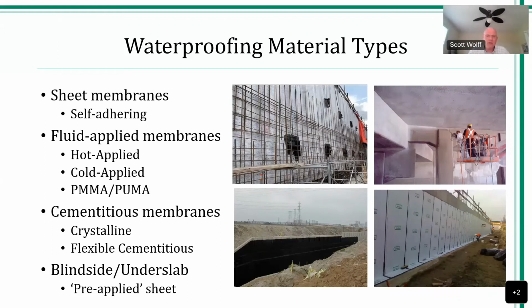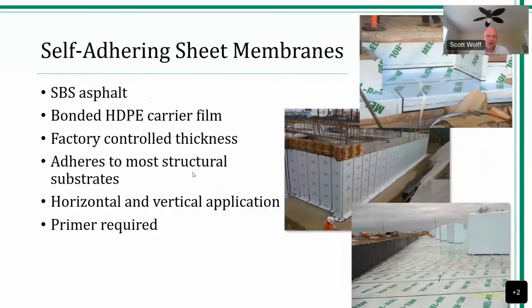And then the blind side under slab systems, the pre-applied sheet, are used again in high hydrostatic water conditions. We had a project on Biscayne Bay that had it 60 feet below grade right there on the bay. So obviously we completely bathtubbed that entire structure. It was a giant aircraft assembly facility. Self-adhering sheet waterproofing membranes are, I believe, far and away the most commonly used waterproofing. It doesn't involve nearly 400-degree asphalt. We can use it for both horizontal and vertical.